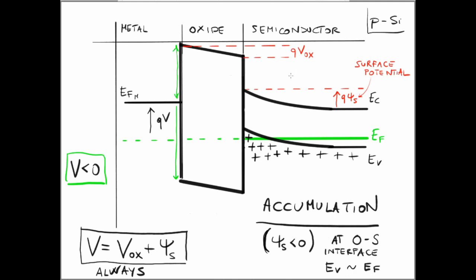What we are indicating here is effectively that this total bias that was applied across the entire device, which we called V, is now split into parts, one across the oxide, one across the semiconductor. And obviously, in such a way always that V is equal to Vox plus ψs. The reason this is happening is that while we have direct access to contact the metal and the far right end of the semiconductor, we don't have access from outside to this interface. So this interface, or at least the potential of this interface, is effectively floating. So the potential V that we applied across the device splits in two.